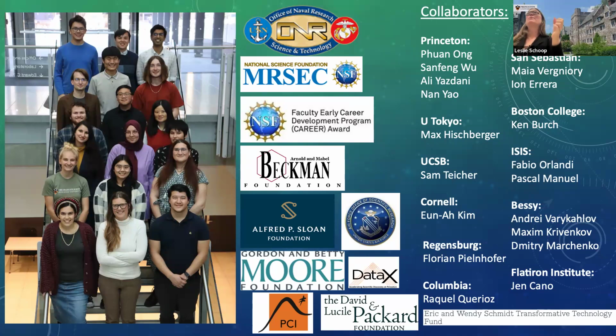I guess maybe you need to put in an additional step, checking whether a smaller disordered version of this exists. There's actually this math guy somewhere in the UK, I forgot which university, who contacted me. He's a mathematician, and he wrote some kind of algorithm based on just finding positions in a crystal, removing all the symmetries, just looking at atomic positions and matching these, and then finding a huge amount of overlaps in this genome database. And maybe that's a way to get out of this problem with the disordered versus ordered structures, so that you realize that these are actually the same materials because the order doesn't exist. But it's like with DFT, it's a hard thing to get around.